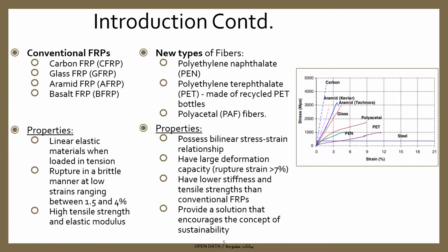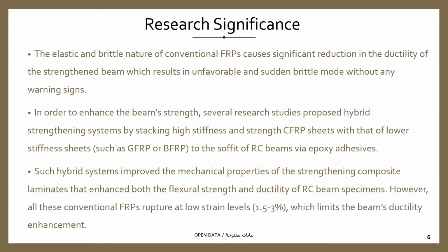However, these types of FRPs have lower stiffness and tensile strength than conventional FRPs, which could be compensated by using more FRP layers. Research significance. The elastic and brittle nature of conventional FRPs causes a significant reduction in the ductility of the strengthened beam, which results in an unfavorable and sudden brittle failure mode without any warning signs.